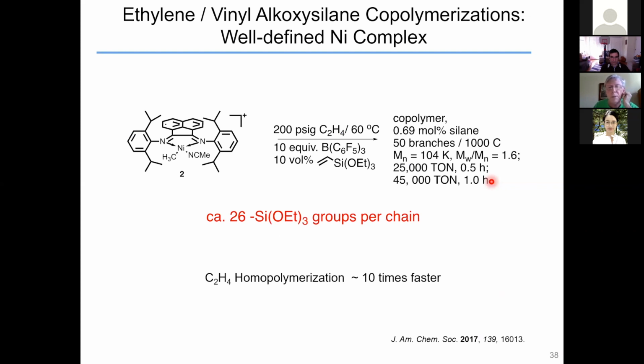The homopolymerization is about 10 times faster than the copolymerization, and the chelate is the resting state. So there is a small issue of opening the chelate with ethylene that reduces the rate.